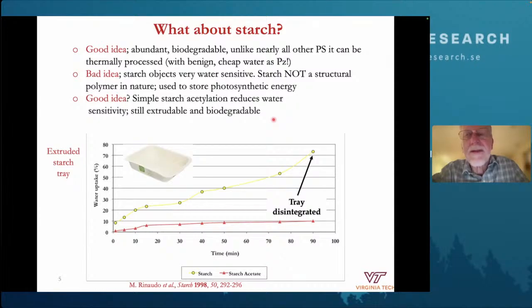We know we can acetylate starch. We can acetylate starch very easily, more easily than cellulose, for example. And the cool thing about that acetylated starch is it's still extrudable and it's still biodegradable at a quite respectable rate, not that much slower than starch itself, right? So, okay, we can reduce the water sensitivity of the starch by acetylating it, and it's still got all these great properties. No, it's a bad idea because starch acetate, like starch, is brittle. It has poor toughness. It's not a very good plastic.